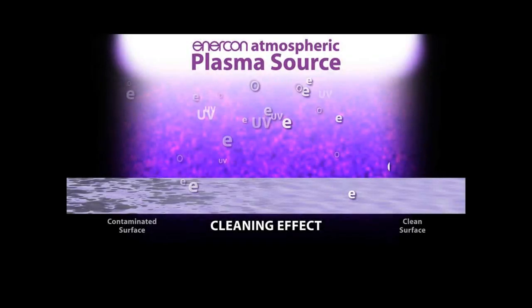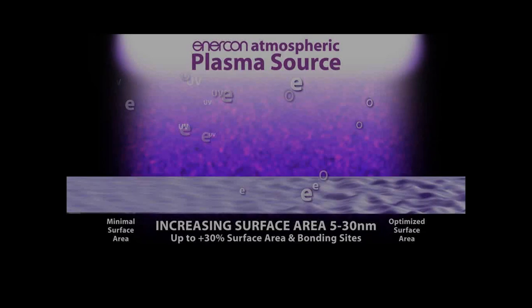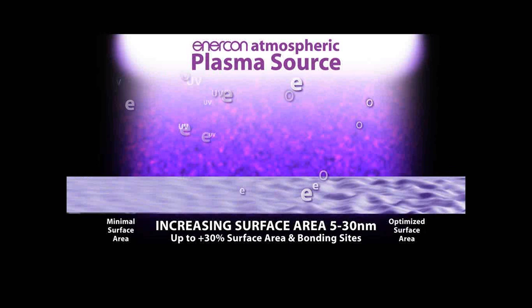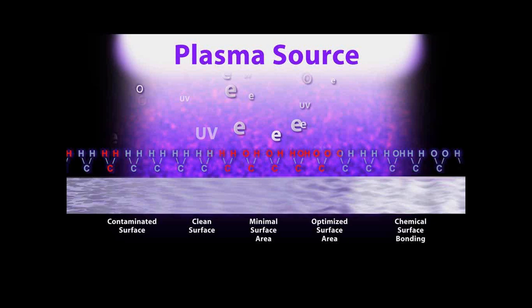Wanted to show you some still frames of exactly what's going on. With every plasma treatment, we end up seeing a cleaning effect where we're removing low molecular weight organics. Ultimately, then, we can create an increase in surface area by the ionic bombardment of the surface, and then ultimately a change in the functionality of the material. So again, just to review all of these, it's cleaning, functionalizing, and increasing surface area.